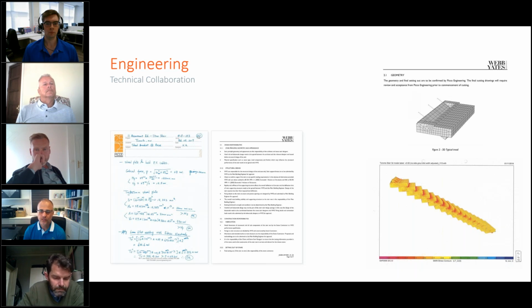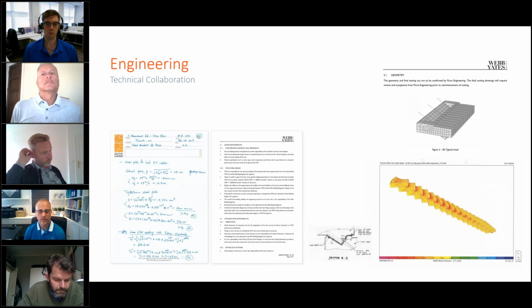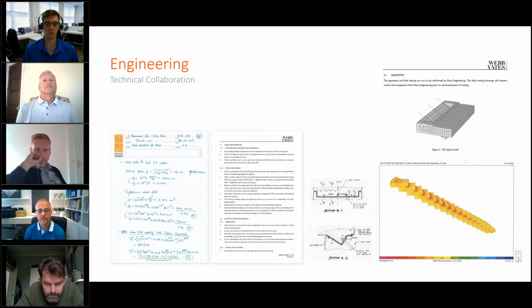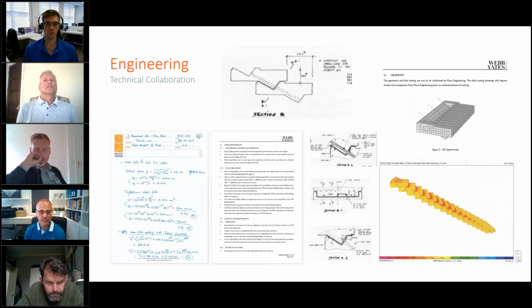So central input to our analysis was the stair geometry, together with the stone test data, which set our modeling drivers. The stair design, having a long and shallow slope, induced a higher bending moment with increased compressive stresses between the treads. So this would require a heavier force specification for tensioning the steel cables during installation. The general concept was to nest each successive tread to the next by way of a shear key. To create this monolithic beam action, we used continuous post-tension steel cables. In this case, 3 half-inch diameter, 7-wire, low relaxation strands with ASTM A416 grade.